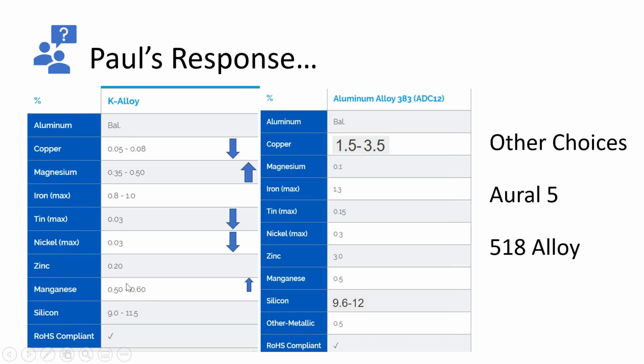Another change is going to be the manganese. So the manganese in the K alloy is a controlled level of 0.5 to 0.6, and the manganese level is a max of 0.5% in ADC 12. So I can have from 0 to 0.5% manganese in ADC 12. This is a requirement, if I'm going to drop this copper level, control the iron level, and pretty much maintain the silicon level, 9.6 to 12 in ADC 12 and 9 to 11.5 in K alloy.